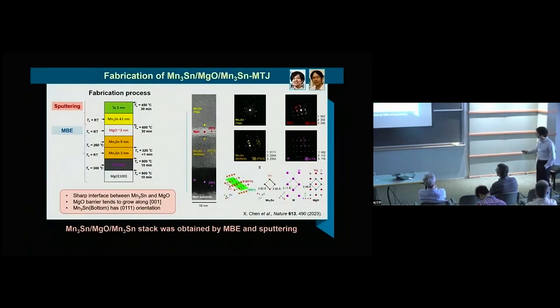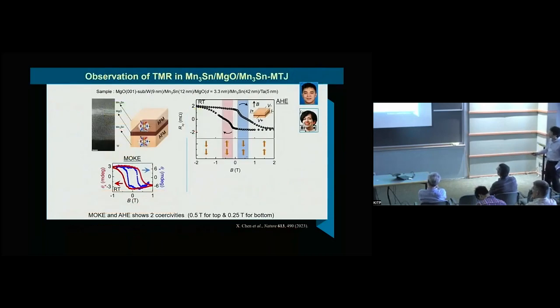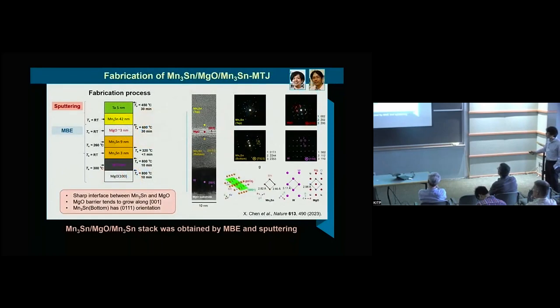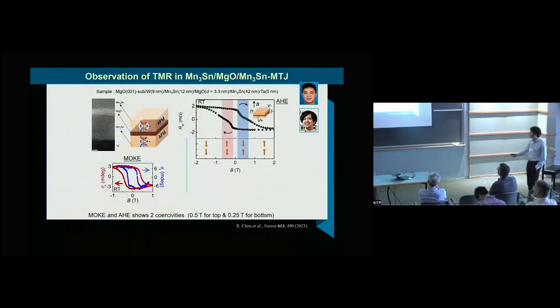A very important point is that the MgO and the electrode magnetic material must have a very sharp interface in between. By applying a voltage, we would like to see a tunneling magnetoresistance. In order to see that, you have to make antiparallel and parallel states of the octupolar moment. For this, we made use of MBE and sputtering, different methods, and we were able to make such different states with electrodes having different coercivity. This is a MOKE, the magneto-optical Kerr effect, looking down from the top, which shows the red curve, and looking up from the bottom, which is the blue one.